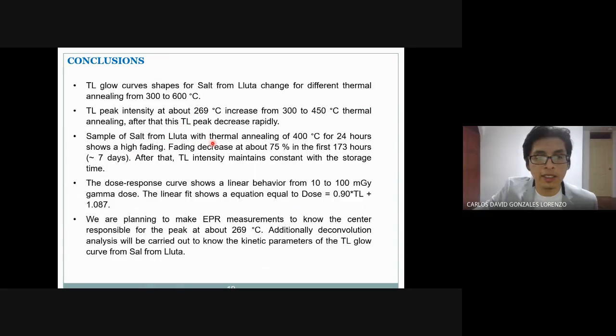Salt of Lluta with a thermal treatment of 400 degrees Celsius for 24 hours, in order to reach a stability of the crystal structure, however shows a high fading. Fading decreased about 75% in the first 173 hours, about 7 days. After that, the intensity remains constant with storage time.